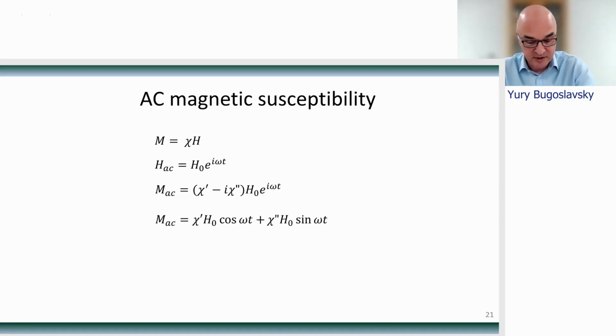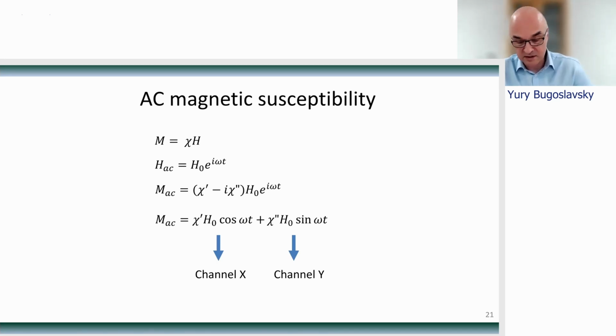The real part characterizes the strength of the magnetic response, while the imaginary is proportional to the energy dissipation which occurs in the sample during a cycle of the magnetic field. If now we consider that we are going to be using the lock-in amplifier to detect these effects, we noted that the first term in this formula maps onto the output of channel X of the lock-in, and the second term maps on channel Y. This makes the lock-in amplifier particularly useful and convenient instrument for simultaneously measuring both components of magnetic susceptibility.